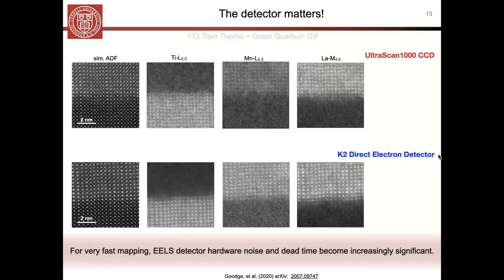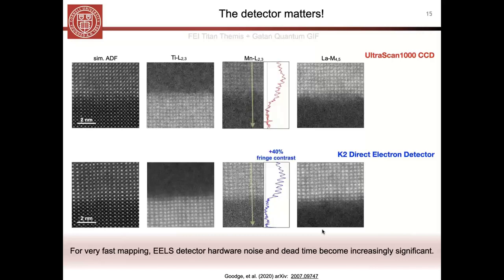Now, if you take that same EELS map, but instead of using the CCD, we switch now. We have also a K2 direct electron detector at the end of our spectrometer, the same spectrometer. And so we can actually take basically the same EELS map now using the direct electron detector. And so you can already see that the signal to noise in these elemental maps has visibly improved, and we can actually quantify this improvement in one way. So here, by taking a line cut across this atomic row, especially in the weaker edges, if we measure the fringe contrast, which is the peak to trough of the part where the atoms are, we can see a 40% increase in this contrast that we're able to extract from these maps.